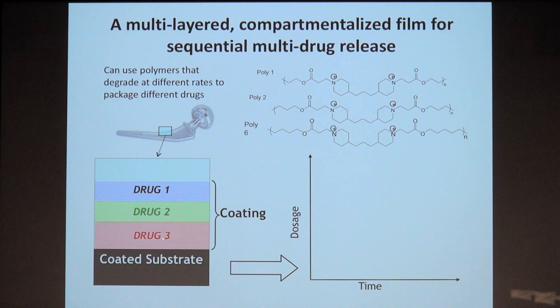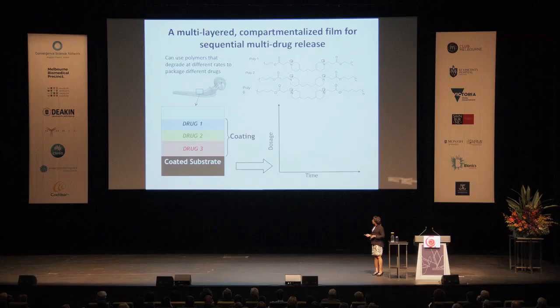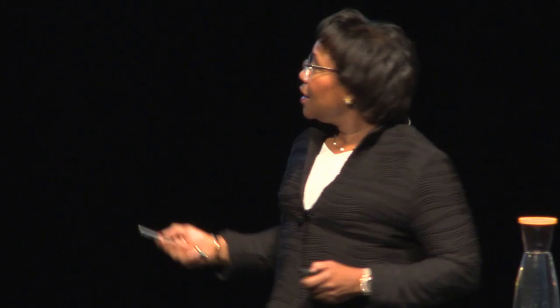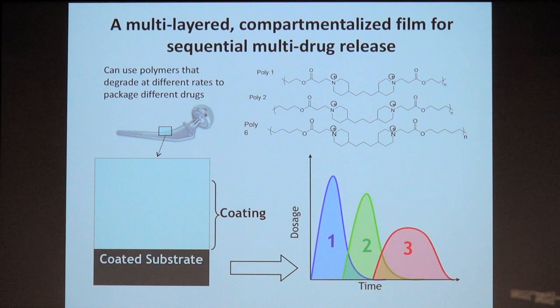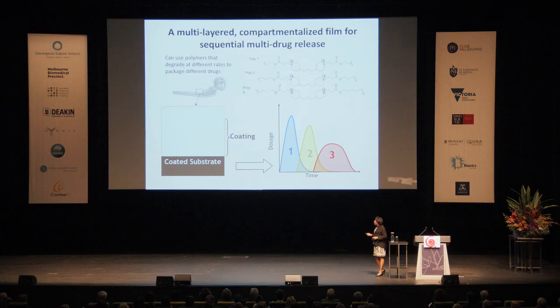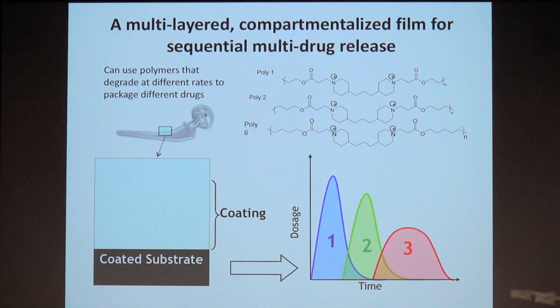If I have a negatively charged drug number 1, I can layer it with one drug. Drug number 2 can be layered with another polymer, and drug number 3 with another polymer, each with its own relative rates of release. I can stack them in a certain way that allows them to release not only with its own relative rate of release, but perhaps staggered over time if I can create barriers between the sets of layers. This means that I can have a much more complex release profile. It also means I can put a lot more drug into an extremely thin space.